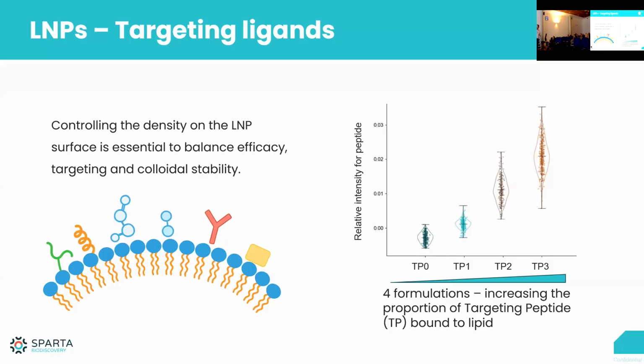So then we look here at the targeting ligands as an example. So this is, of course, a big field that's coming up. And what people are doing is they have a similar core composition and put in different ligands on the surface. So we worked here with a company, and here we have the TP0, which is where they had 0 amount of targeting ligand, and we measure that signal. So it's very important with SPARTA that we measure a controlled sample that, for instance, doesn't have a certain component or doesn't have the targeting ligand as a baseline, because that baseline might not necessarily be absolutely 0. And there will be a bit of noise variation there. So then we add a small amount of targeting ligand, and we can see that formulation go up.